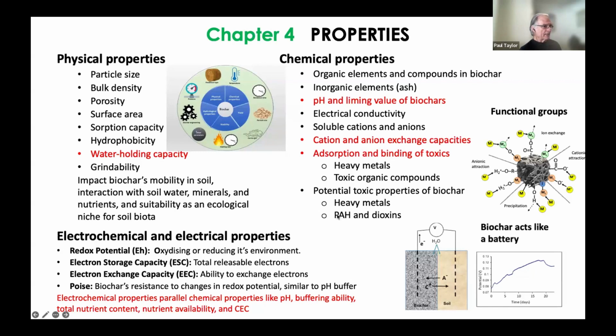However, if you choose the biochar so it's made from materials that are not loaded with heavy metals, we find that there's not very many in there, and in fact most of them are bonded strongly to the biochar. And if you look for the plant available component of those toxic components by doing leaching studies, it's actually extremely low. It's often undetectable. It's below the 1% level, and you could probably apply biochar in agriculturally relevant quantities for hundreds or thousands of years before you built up a level that reached the limits.